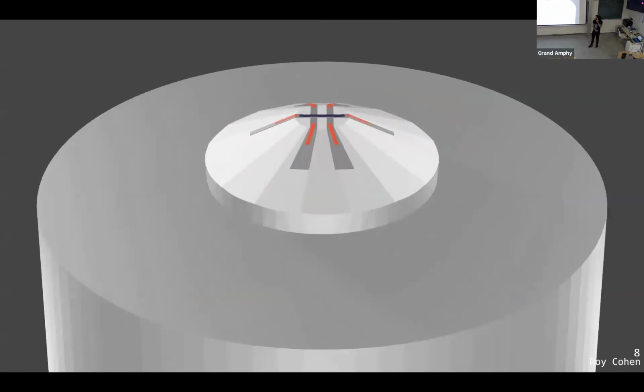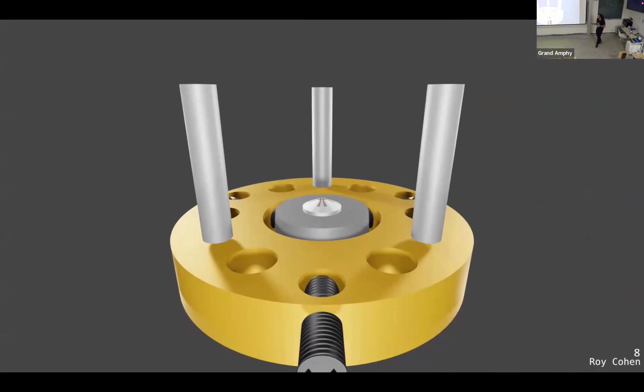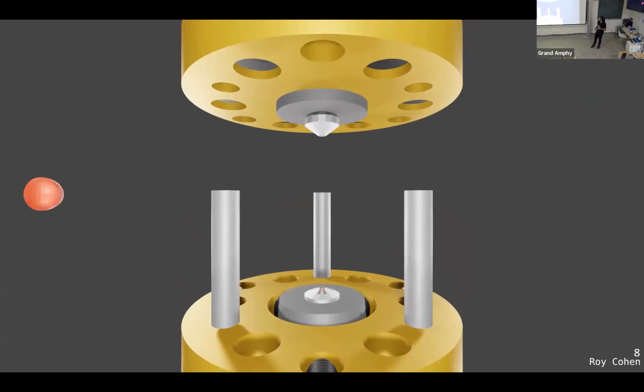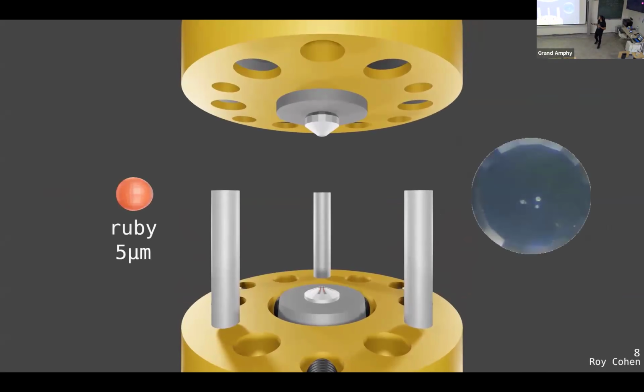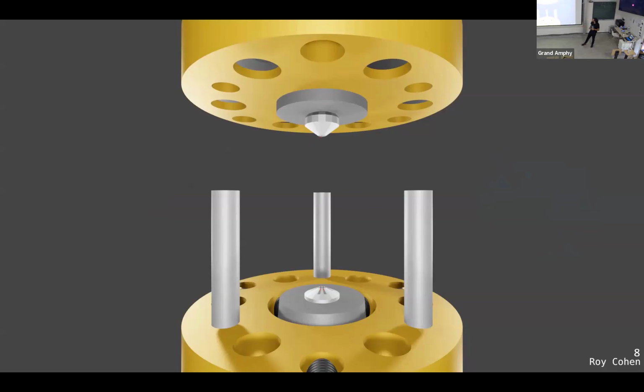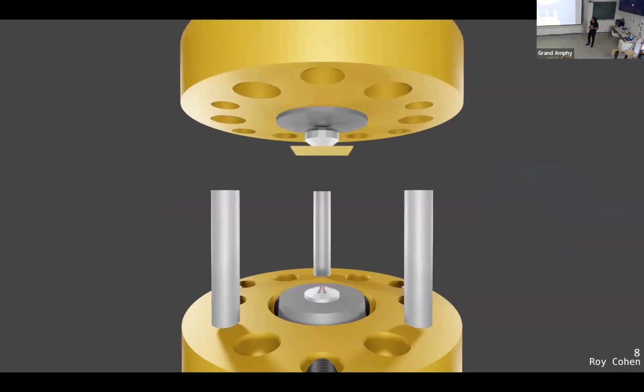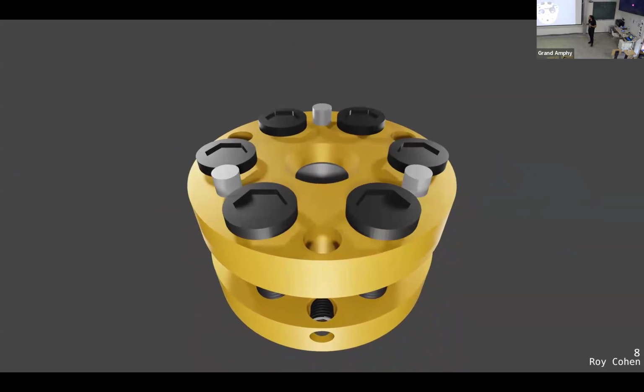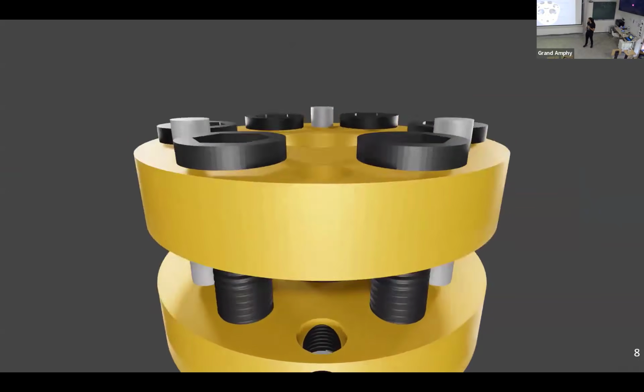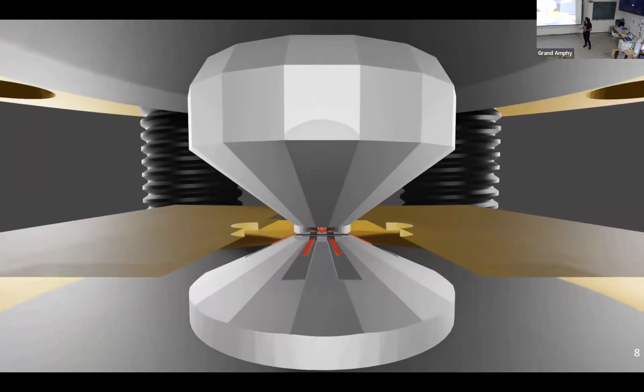Lastly, we put our diamond back in the DAC. We add ruby spheres, as we can see here, those tiny ruby spheres, to be able to measure the pressure inside our diamond anvil cell. The fluorescence of the ruby is very tunable by the pressure. And then we can close our diamond anvil cell once again. We have a picture of our final sample, and we are ready to go.